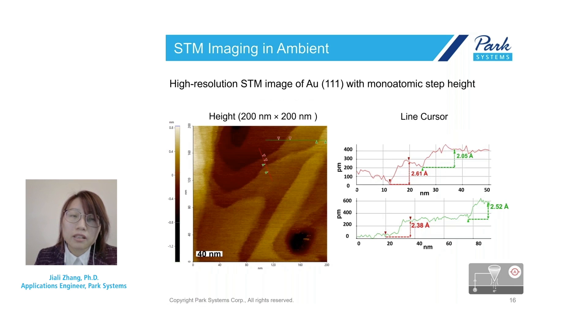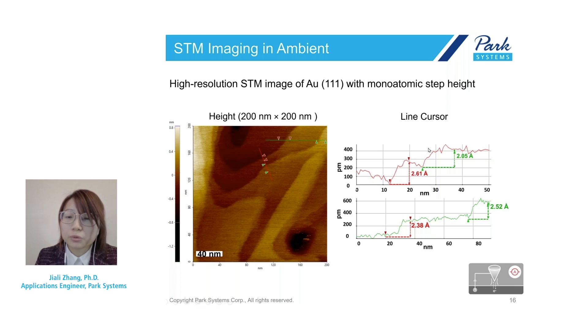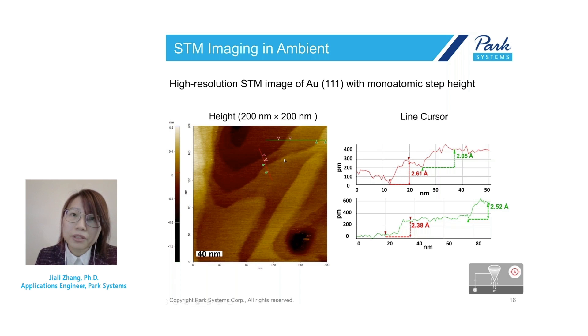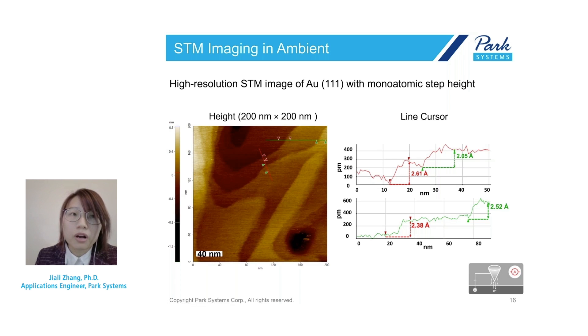Zooming further into a 200×200 nm image area, the gold step height of this atomically flat (111) terrace was quantified using a line profile in our data analysis software XEI. This profile shows the flat terrace has a single gold monolayer step height of about 2 to 2.6 ångströms, which is in good agreement with the theoretical value for monolayer gold thin film height.